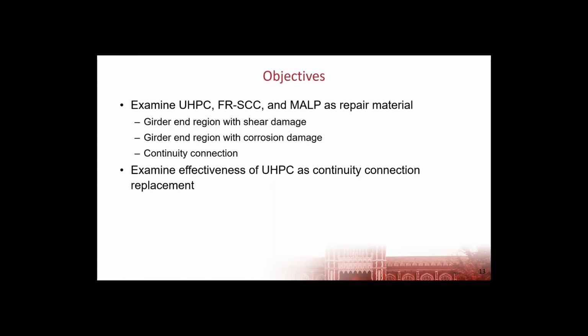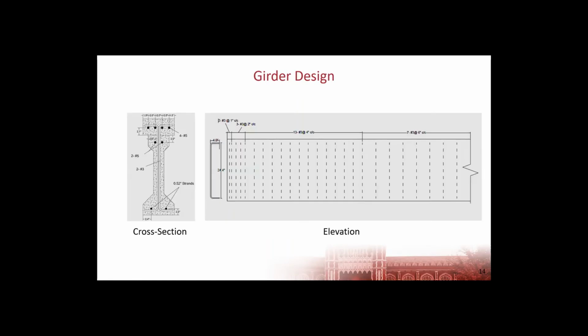So in terms of looking at the end region repair, we used an approximately half-scale pre-stressed concrete girder specimen that had two half-inch special pre-stressing strands. It had a composite deck section that was designed to simulate a half-scale bridge deck. But we increased the depth and shortened the width of that section so that we could get the same flexural capacity with a smaller overall section. It included shear reinforcement that was designed to produce a flexural failure at mid-span.